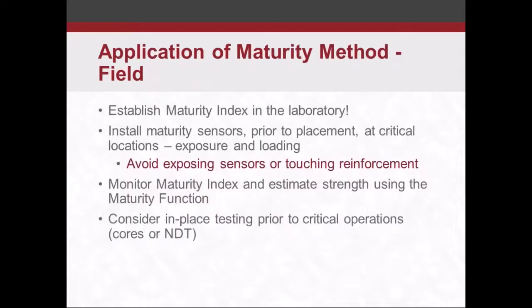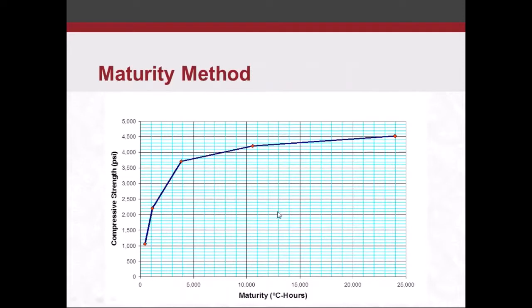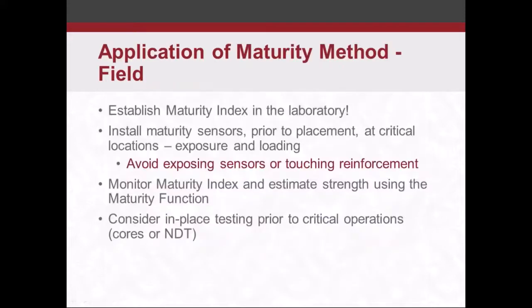And then to apply it in the field, we've established that maturity index, which is the previous graph. We take maturity sensors prior to placement, put them at critical locations, maybe in a pier or footing or something like that. And then we monitor that maturity sensor as the concrete cures. And if we want to figure out what the strength is at 7 days, we download that sensor. We see where our maturity falls on this line, and then we figure out what the compressive strength is.